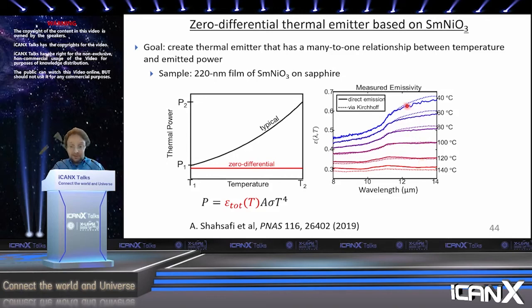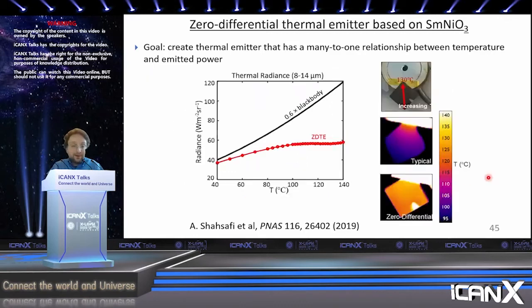And in fact, it turns out that this decrease is at just the right pace to achieve the zero differential effect. So to see that, we integrate the thermal emission spectrum over 8 to 14 microns, and we plot the integrated radiance versus temperature. And you can see that over here, between about 100 degrees Celsius and 135 degrees Celsius, you have this zero slope, the zero differential effect, which means that irrespective of the temperature, your amount of thermally radiated power is the same. And so we've achieved our goal.